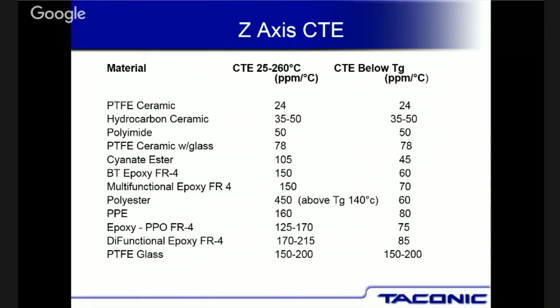You can see it expands at 85 parts, looking at the difunctional, 85 parts per million per degree C below the T sub G, and it could be as high as 215 parts per million once it gets above the T sub G of the material. But every material has a thermal expansion, and this just represents the different materials' thermal expansion below and above the T sub G of the material.